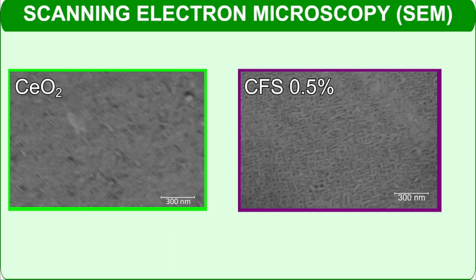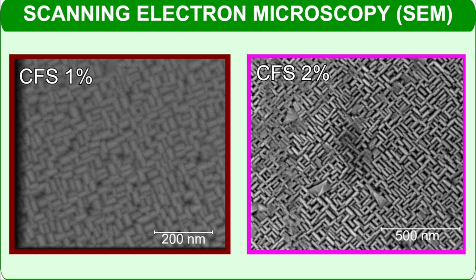We analyzed the surface of our films using SEM. Our CeO2 film exhibited a surface with some roughness, which was in line with our expectations. But the images of the 0.5% CFS doped film presented formations of a maze-like pattern on the surface, composed of small CeO2 grains that wasn't expected. Upon conducting SEM imaging of the 1% and 2% CFS doped films, the same maze-like structure was present, and the grain size increased with the amount of dopant. In the 2% film, we also observed the emergence of triangular patterns on the surface.